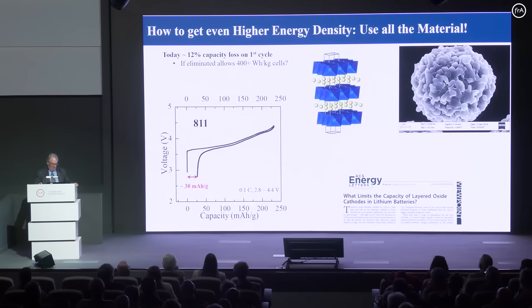Let me go back and make a point. What we've determined is that this is diffusion related. So these atoms jump depending on the vacancies. We describe it as the same situation as, say, in a conference room like this one. If 80% of all the seats are full, the empty seats are invariably in the middle of the rows. So if you want to put an extra person in, everybody has to move. It's exactly the same in these materials. So to get the last bit in there is much harder than the first part.